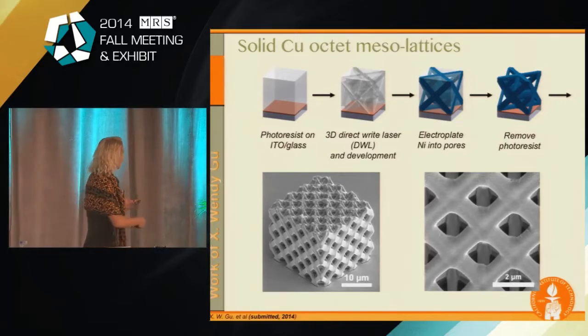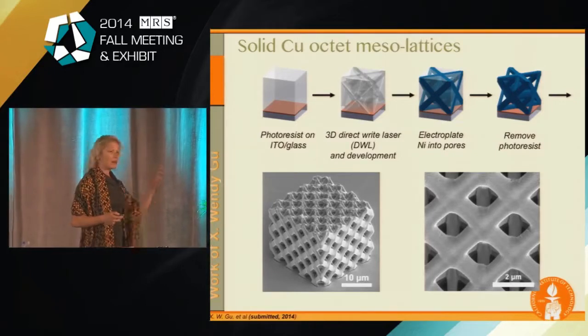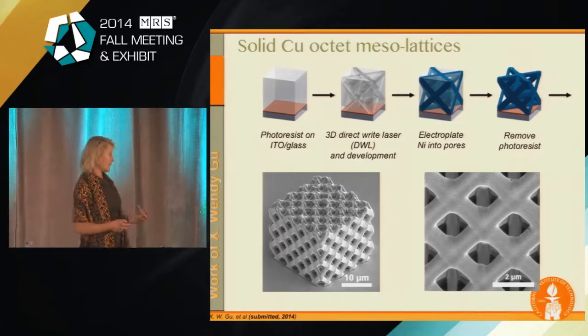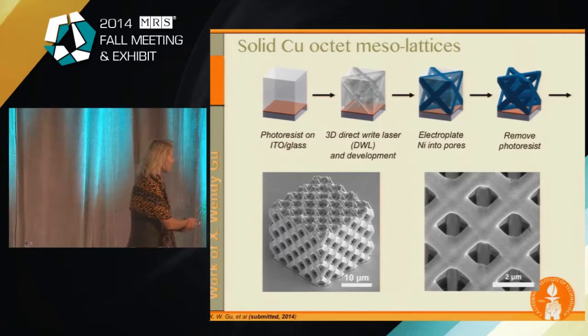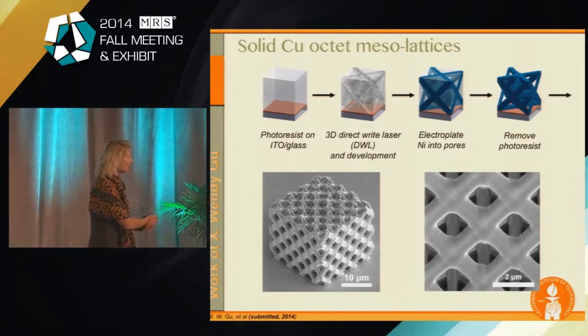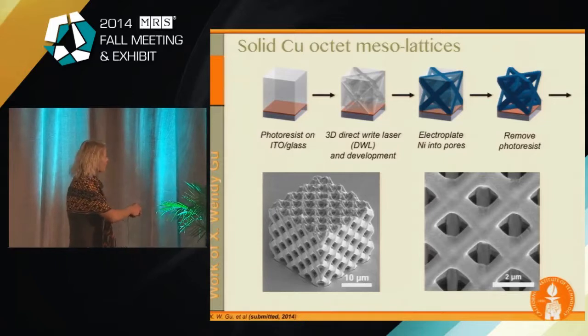So my student at the time, my student Wendy, figured out how to make these monolithic metallic lattices. And now these are no longer nano lattices. These are actually meso lattices, because if you look at the unit cell, it's about 2 microns. So Wendy figured out how to do an inverse of the process that I described, and so she opened up these holes in the resist, and then she electroplated into them.